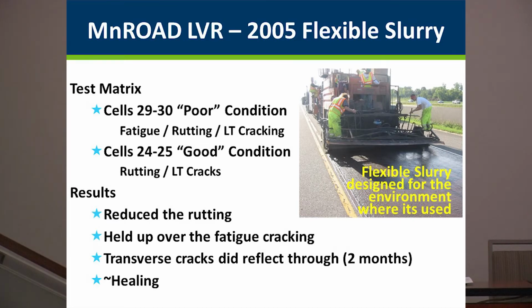two test sections where we had a poor condition road for two cells, a very poor condition with fatigue, rutting, low temperature cracking, something that you would never put a microsurface or type of treatment on. And then we had some sections that were in better condition. And really the difference was the fatigue cracking. But we saw that when we did a flexible microsurfacing, we were very surprised and very encouraged that it seemed to kind of bind the road together and buy you some time.